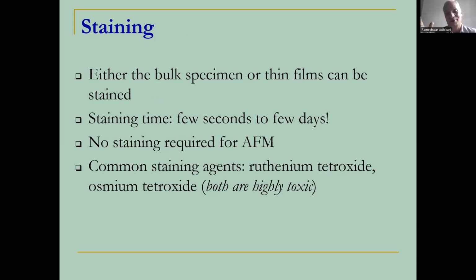So it is difficult to stain only carbon and only hydrogen. Not possible. In my knowledge, it is not. It's not possible today. I don't want to say impossible. Today, it's not possible for electron microscope. But if you have polypropylene and polyethylene, by virtue of their high molecular weight, they do not mix. The entropy contribution is too low. In that case, they segregate. Even in that case, it is difficult to image them separately, because the contrast between polyethylene and polypropylene is very, very low, because the density of polypropylene and polyethylene is not very different.